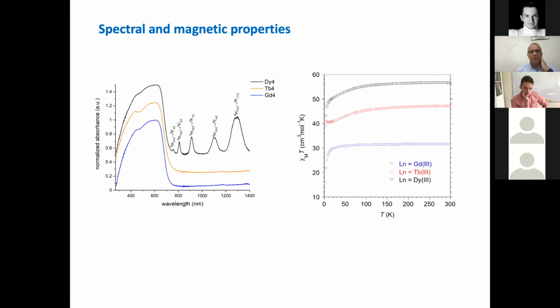So the magnetic properties and the spectral properties have been investigated. The spectral properties, especially for dysprosium, just to emphasize the f-f transitions, are presented here. And on the right, the magnetic properties are displayed for gadolinium, terbium, and dysprosium. For the gadolinium compound, you observe an overall antiferromagnetic interaction, while for terbium, we observe at low temperature a slow increase of the chi T product.